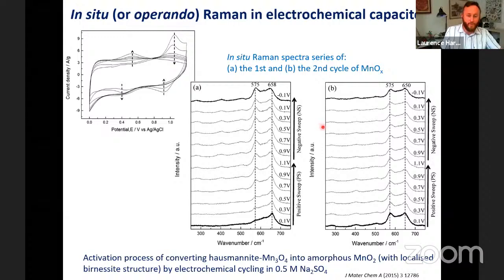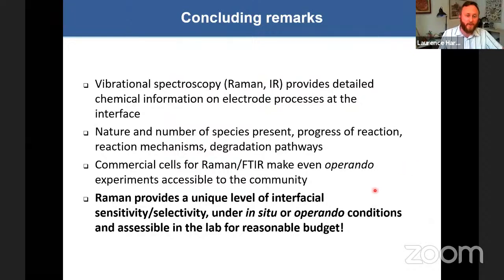Finally, to highlight, we've also been looking at certain manganese oxides for pseudocapacitors, and this is just an example of where we've used it very nicely to show how this manganese oxide, mainly Mn3O4, can be electrochemically converted into a manganese oxide which gives much better pseudocapacitance by electrochemical cycling. We see here how the capacitance improves as you cycle, and we've used the spectroscopy to look at how the different Raman bands vary as you cycle, and we can observe the change in the spectra.